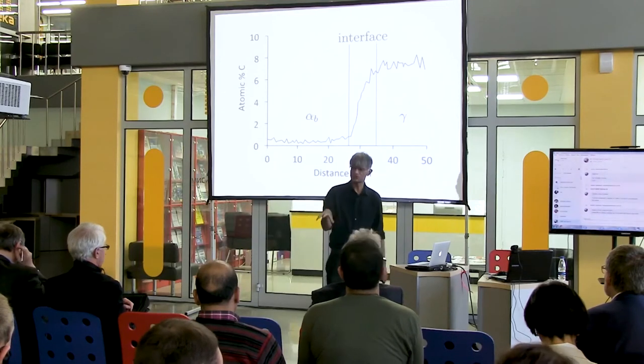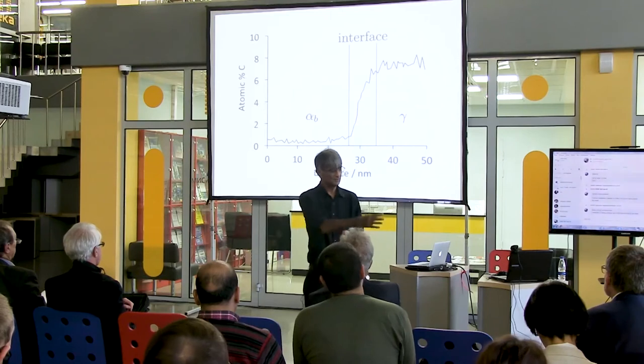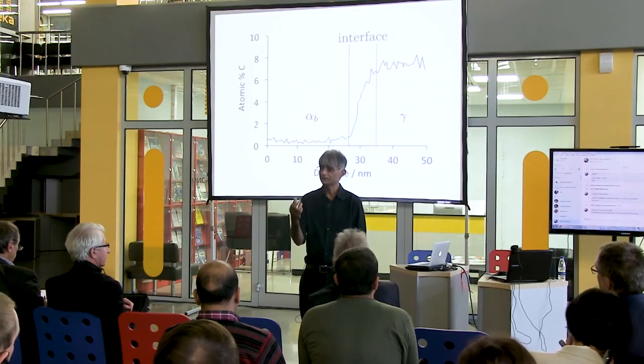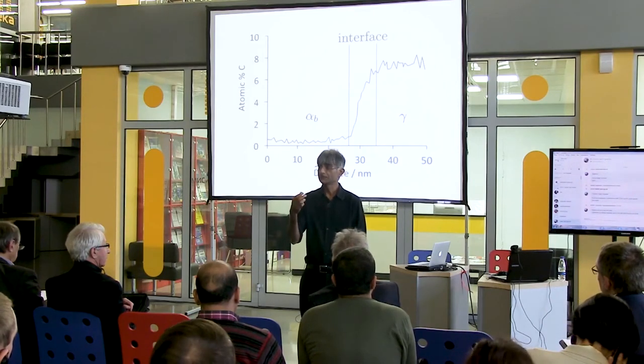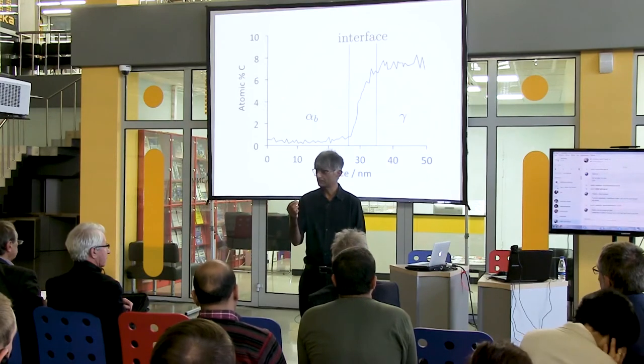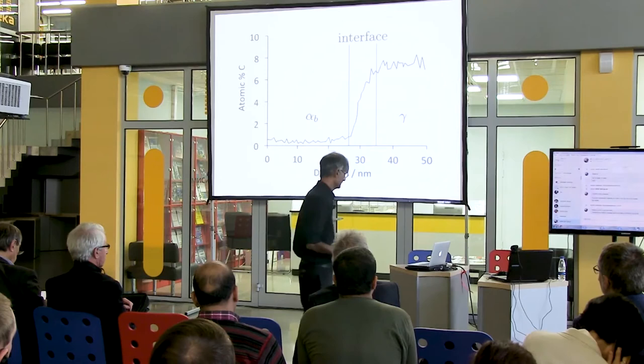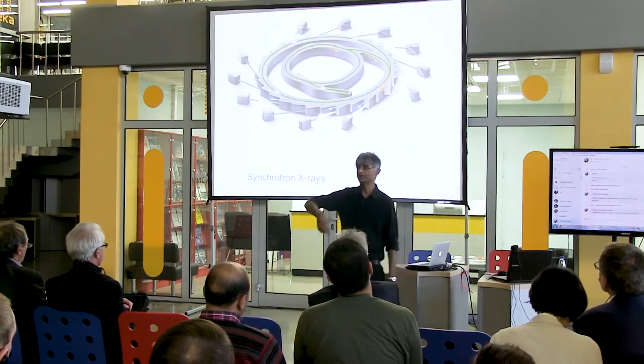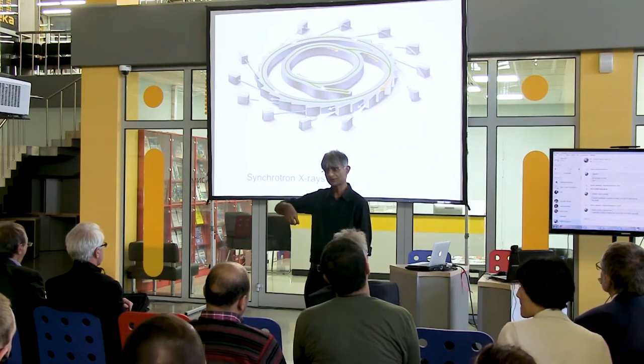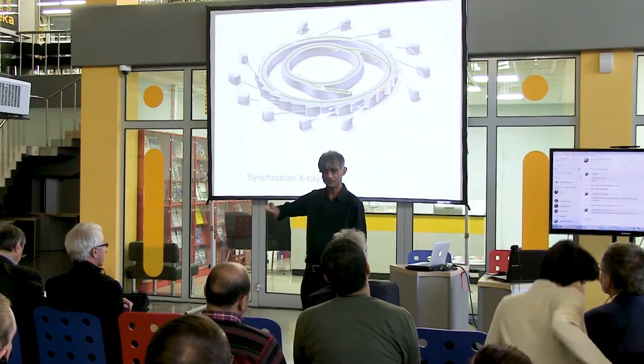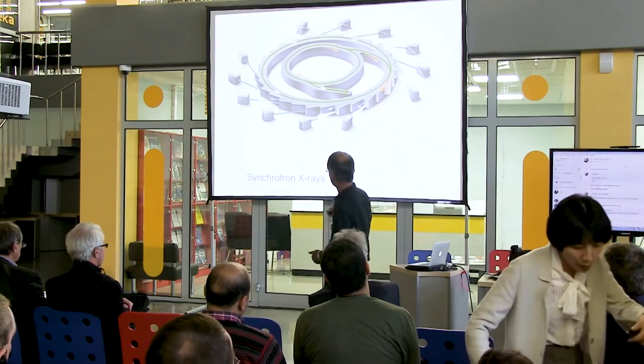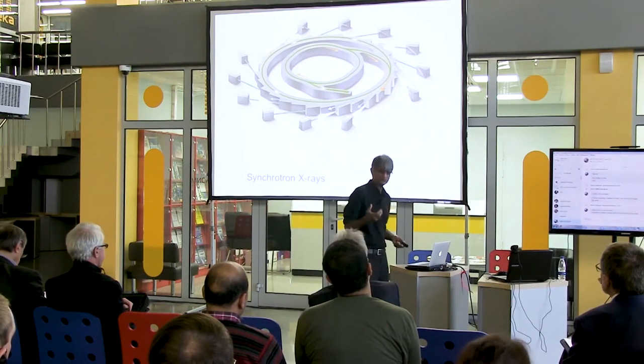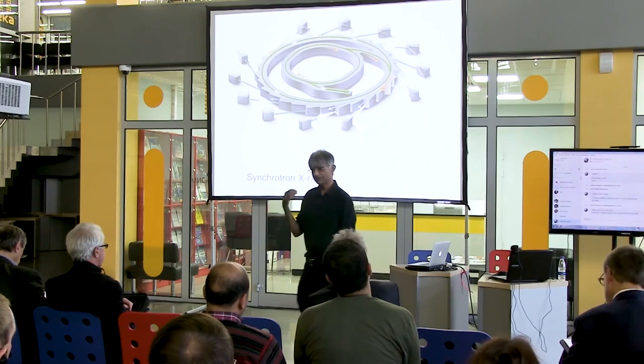We want to look at a larger amount of material. We have techniques in which we can examine a 10 millimeter thick sample. Synchrotron x-rays are very powerful and can penetrate 10 millimeters of steel. A synchrotron is basically electrons accelerated around a ring — when you accelerate electrons, you get very high energy x-rays. These are effectively beam lines where you're pulling off x-rays to do experimental work. The advantage of this is you can rapidly get diffraction information — you can transform the material and take a diffraction pattern every second.